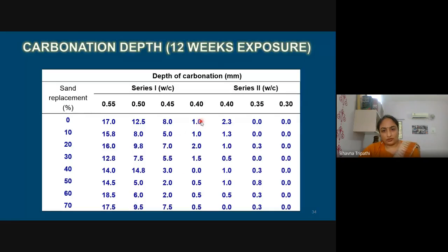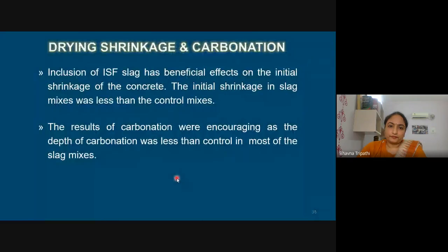And if we look at the lower water cement ratio mixes, you can see clearly that the depth has reduced. What I want to emphasize is that the results of ISF slag with relation to carbonation, shrinkage, and the durability evaluation are promising. So, to summarize shrinkage and carbonation, both the properties supported use of ISF slag up to 70%.